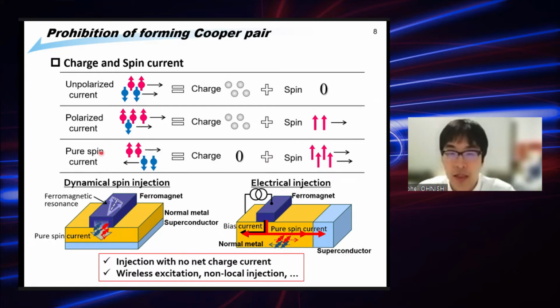This pure spin current can be induced, usually by dynamical spin injection or electrical spin injection. The largest advantage of the pure spin current is that there is no net charge component. By this, we can ignore the heating effect in these structures. And also, especially in the case of dynamical spin injection, we can fabricate wireless samples for measurement. And in the case of electrical spin injection, we can perform non-local spin injection. In today's presentation, we use this electrical spin injection.